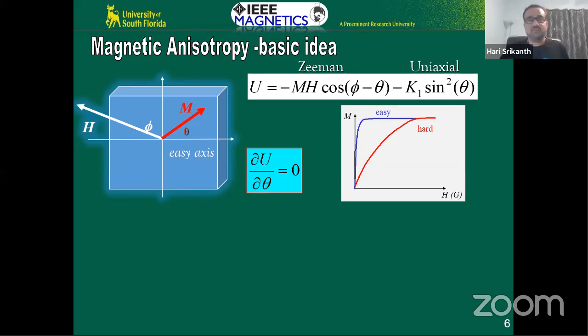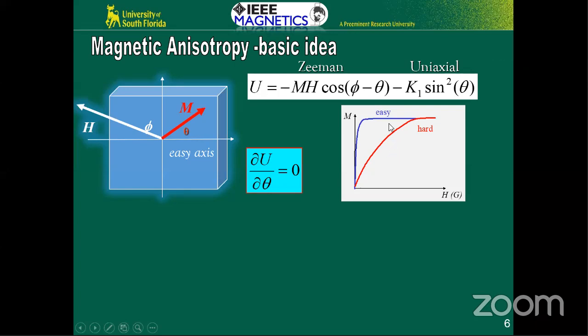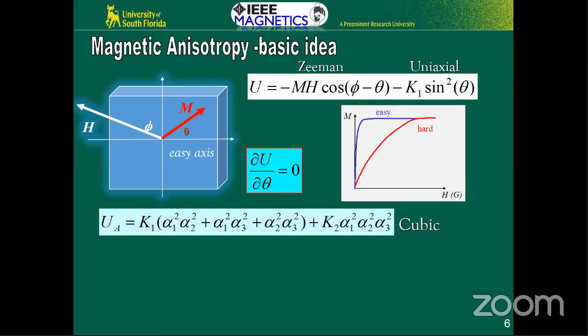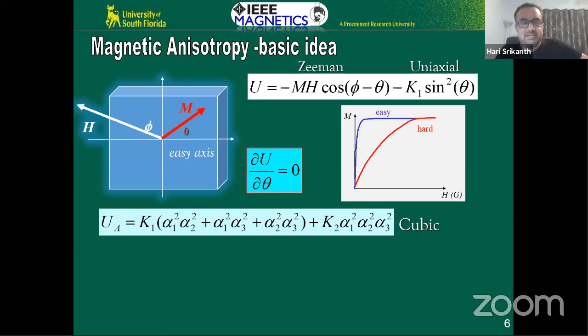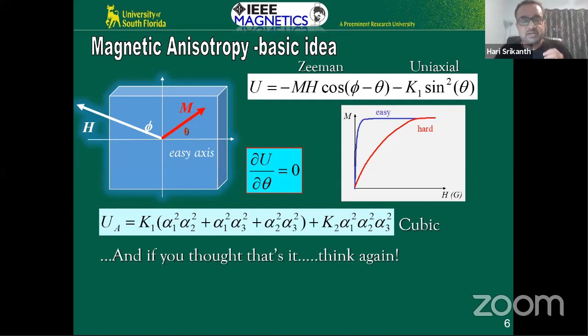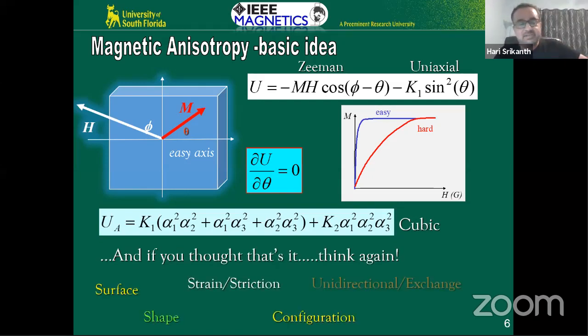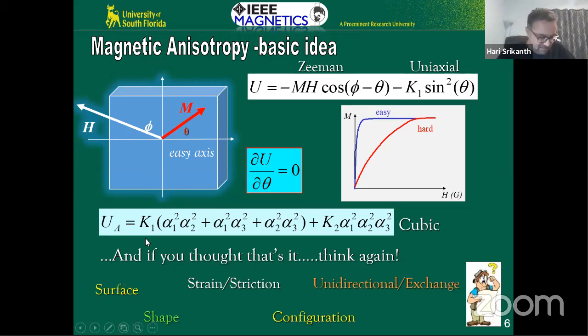Okay, so well, what about the structure? This is simple uniaxial anisotropy. There is a preferred direction here, which is typically the case for most spherical or symmetric nanoparticles. However, we can also handle higher order symmetries, cubic, for example, no problem there. We can take the different directions and do that. But when it comes to nanoparticles, there are many aspects that go into the anisotropy. For example, let's start from the left here. You see that the surface is